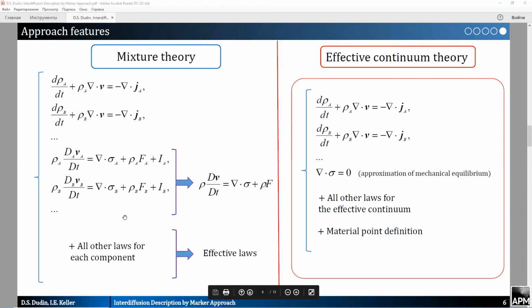Then we can go from the component balance equations to the equations for an effective continuum. From a phenomenological point of view, this procedure seems unnecessary. Therefore, an alternative approach arises, presented on the right side. It's named the effective continuum theory. It's based on the hypothesis of an effective continuum particle. It allows us to also write the balance equations of mass for each component and other necessary laws, but for an effective continuum initially.